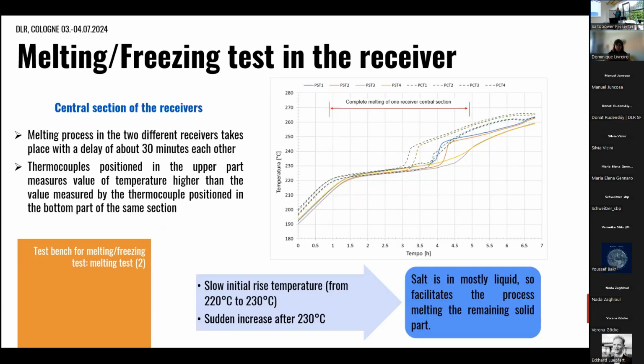If you want to see in detail the different sections of the receiver, we can see that at the center section the process starts at different moments in one tube and in the other tube. More or less, we have a delay of about 30 minutes, and this depends on the configuration of the two receivers. We suppose it is due to the inclination of the line.